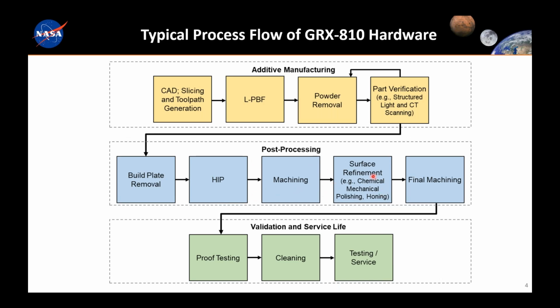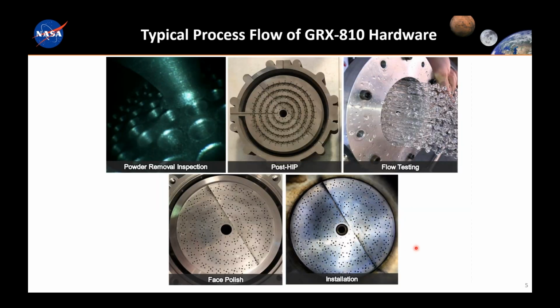For some of these components that we develop, we've gone through machining on these, and again, GRX 810 machines similar to some of the standard nickel-based superalloys. We've also developed some of the surface enhancement processes, which I'll highlight in a slide a little bit later. And of course, proof testing, cleaning, and then putting this into service. So I think what you see here again is it follows a very typical process flow. There's no unique processing. If anything, there's actually reduced processing on this because you go through a HIP and then the material is ready for use. So you don't have to go through any sort of solution or aging or anything that Tim highlighted.